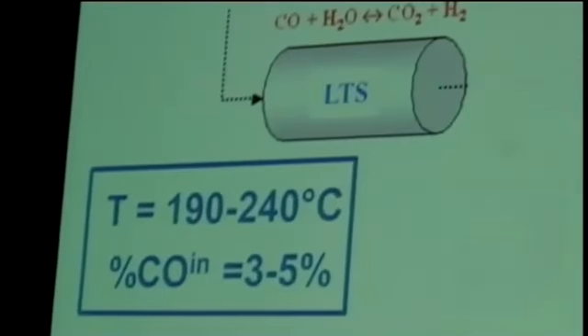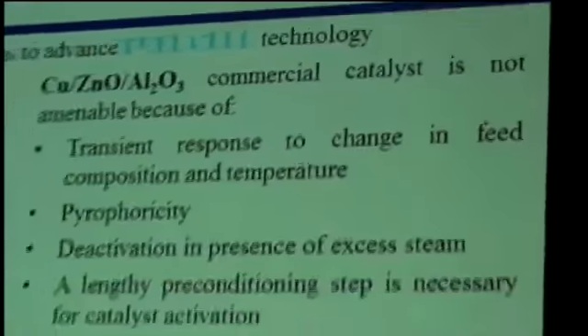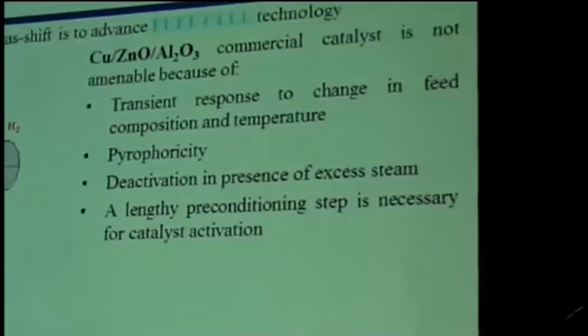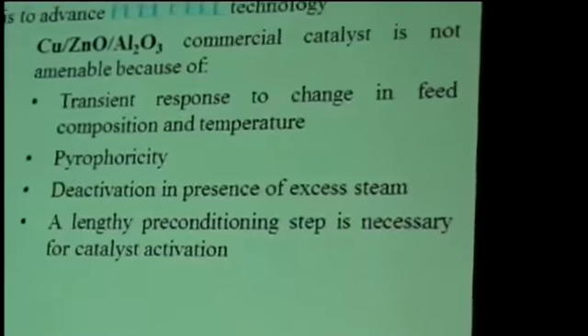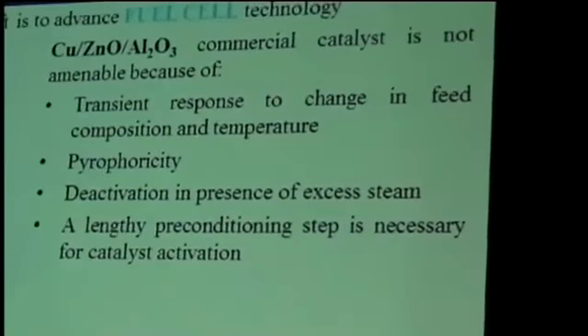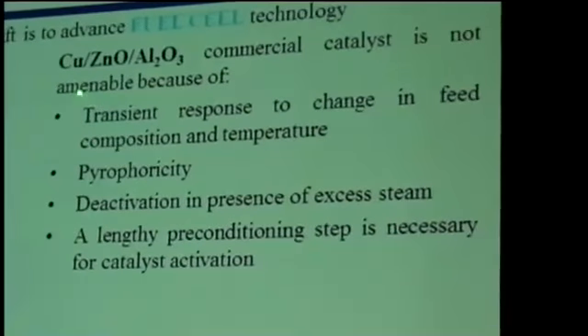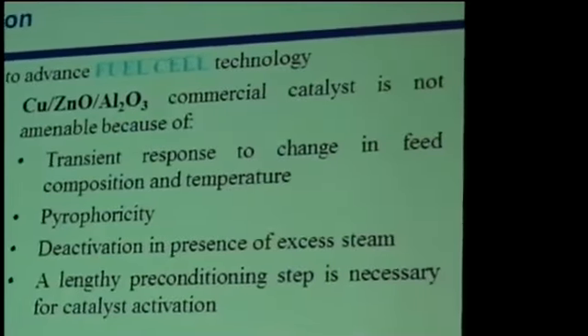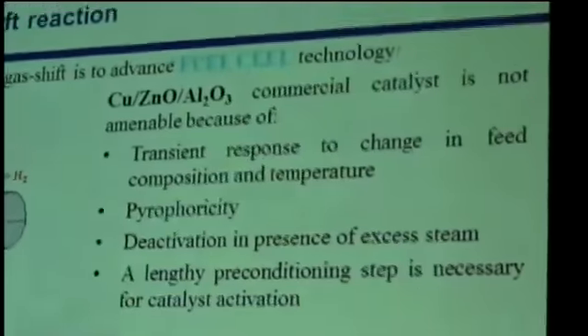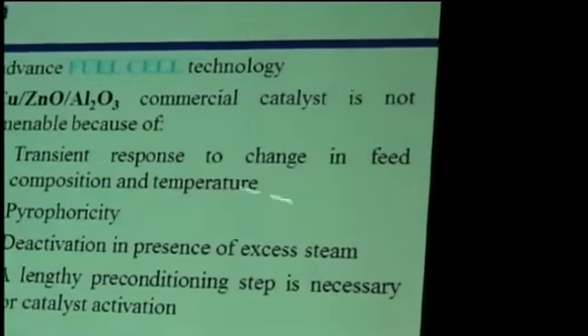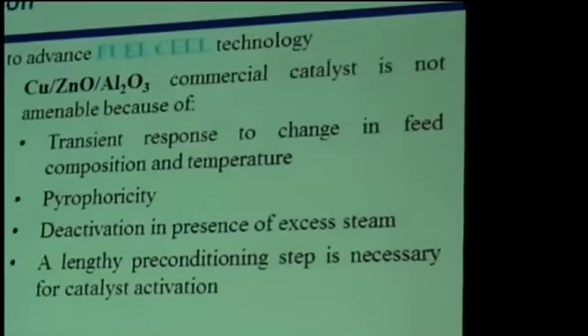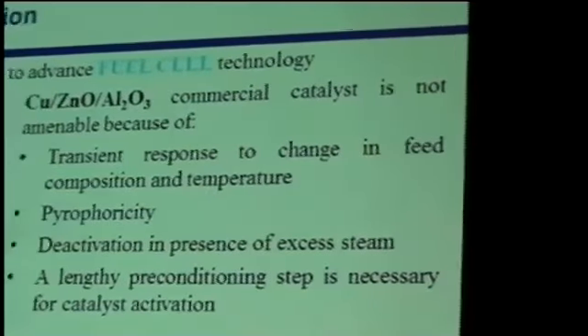And the conventional low temperature shift catalyst, and here we are talking about low temperature shift where we're taking 3 to 5% CO and converting it to below 1% CO levels, which could possibly be handled by a preferential oxidation cleanup system or selective hydrogenation. And the conventional catalysts have some problems for fuel processor applications: problematic transient response curves to changes in feed composition and temperature, also pyrophoricity, deactivation problems in excess steam, and preconditioning steps.